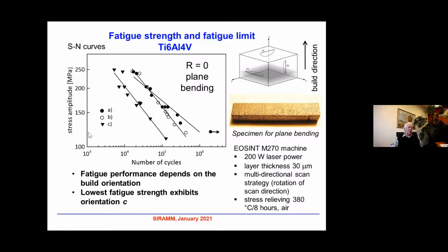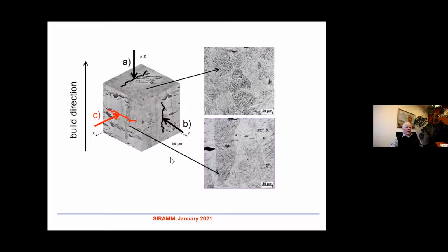For example, if the loading would be of a component for treating a human pelvis, let us say 120 megapascals, then after 10 to 5 cycles the component will fail. However, if the orientation is A or B, the specimen will survive. So I would like to conclude that fatigue performance depends strongly on the build orientation, and in this case, the lowest fatigue strength exhibits orientation C. Once more to show the situation. So when it is the build direction, when the crack initiates here, so it propagates practically through this material, through the structure, the lifetime is worst.